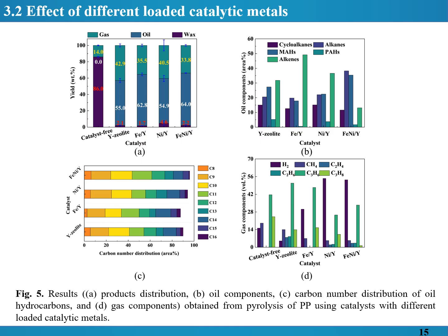And the double dope of iron and nickel also showed the highest concentration of C8 to C16 hydrocarbons, reaching 96 area percent, exceeding the previously reported value of 91.02 area percent. The double dope of iron-nickel catalyst achieved the highest hydrogen concentration of 53.44 volume percent in the produced gas, which compared to natural gas results in a reduction of carbon emissions by 11.68%.